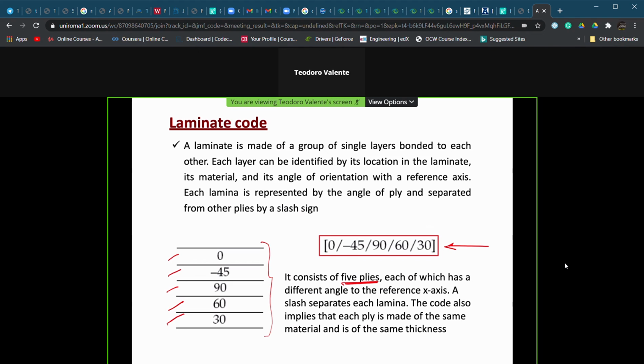And when we use this expression, that is 0, minus 45, 90, 60, 30, which is reported in brackets like this, this means that this first layer, according to our coordinate system, is a layer for which, for example, if this is our coordinate system, the fibers are aligned along the X direction. We are not going to take into consideration Z for the reason we have said before.